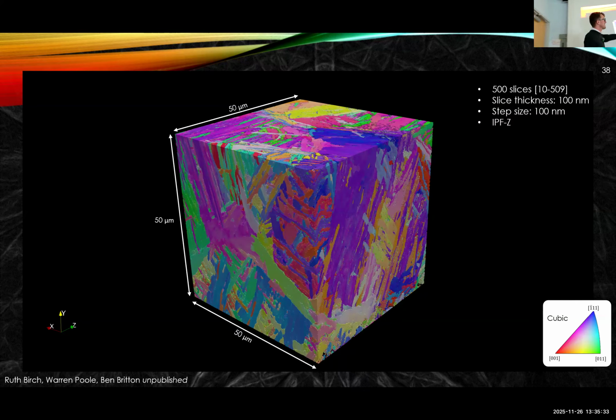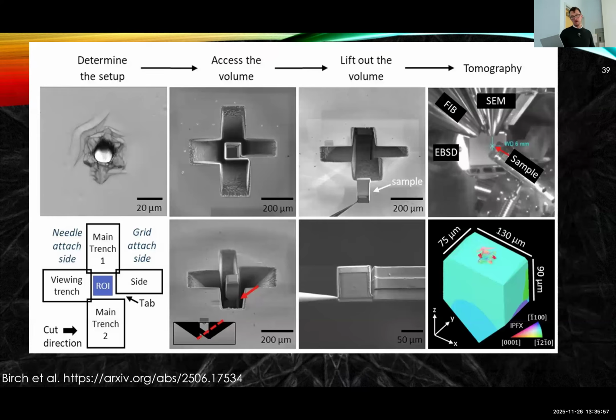This is 500 slices. Each slice thickness is 100 nanometers. The step size in each plane is 100 nanometers for this object. And we've reconstructed to give us a 50 micron by 50 micron by 50 micron cube. The newer data sets, we vary between like 20 micron up to maybe 250 micron if it's a good day. It might not be 250 in thickness, but certainly it's possible.